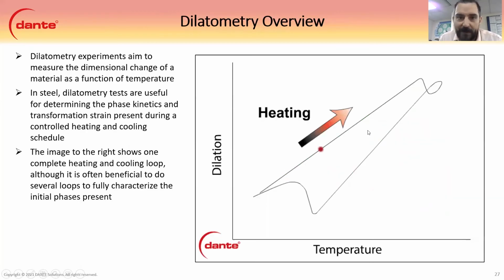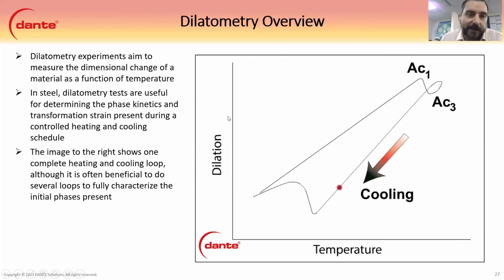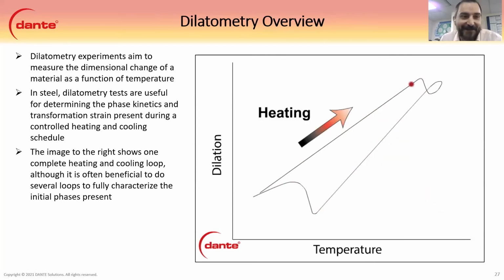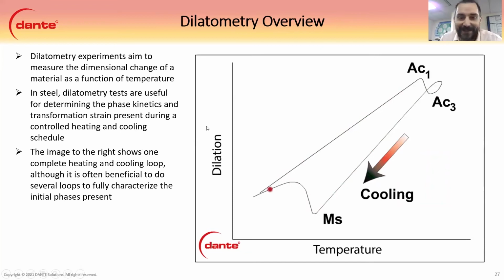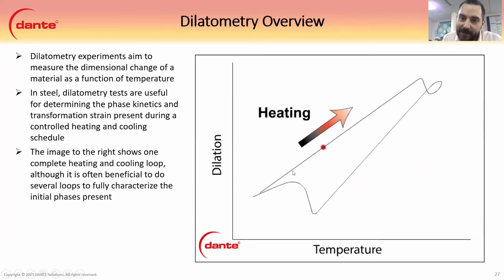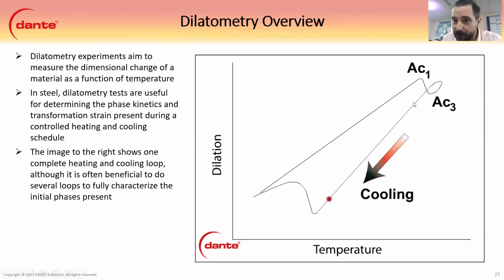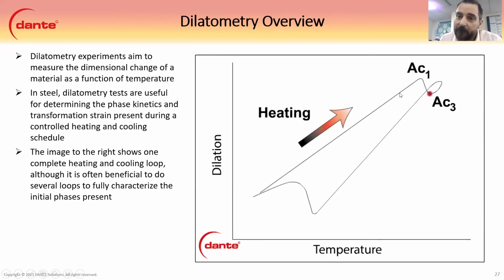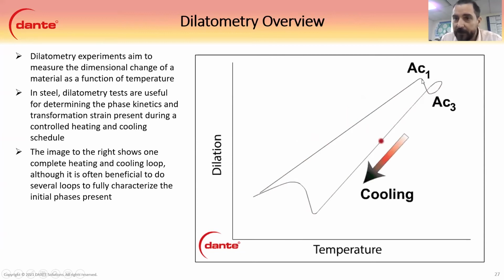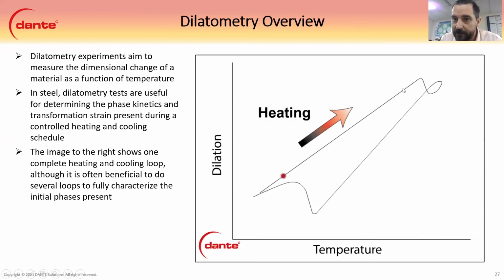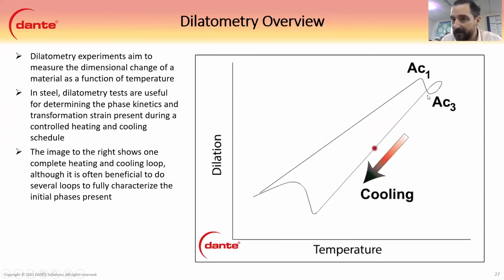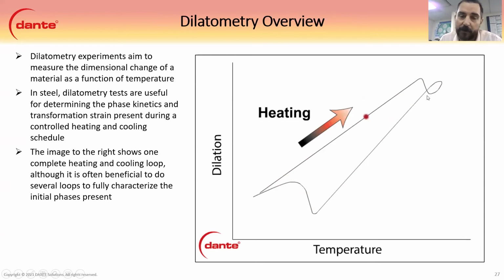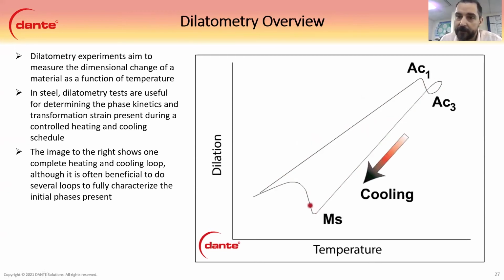Now, let's talk a little more about dilatometry data. So dilatometry experiments aim to measure the dimensional change of a material. So they heat up a material and they have a measurement on it, and as it heats up, you can see that in this heating section, it actually grows, right? And so once it reaches austenite temperature, it'll drop a strain, a dilation, right? And that volume change tells us a lot about the austenite formation, when it happens, what time, how big the strain is. That's why we prefer the dilatometry data when we fit these experiments, because we can get a lot of information from it.